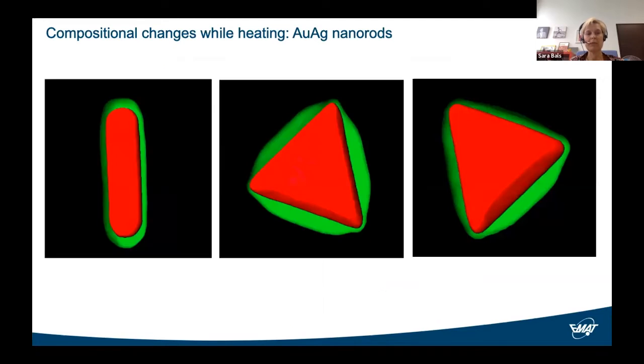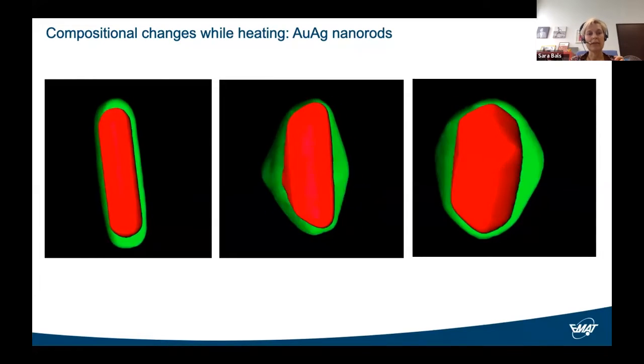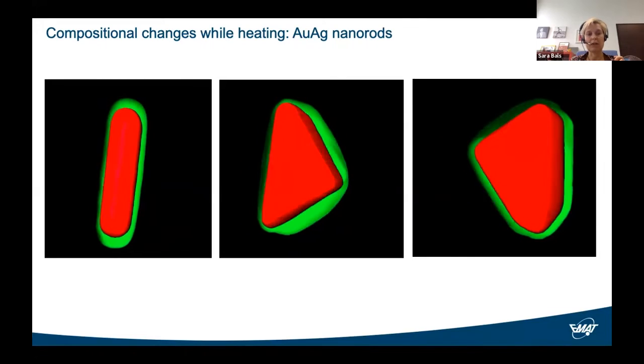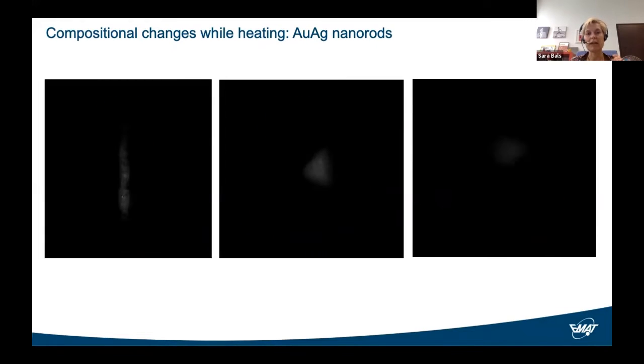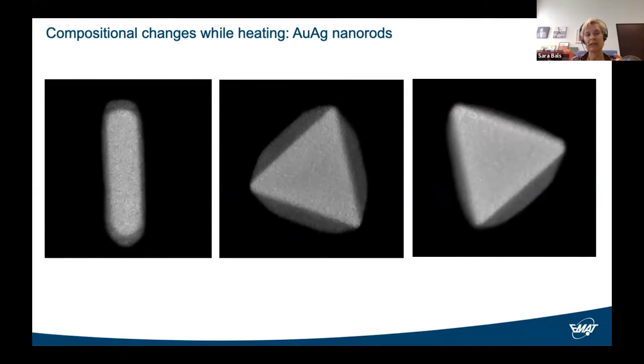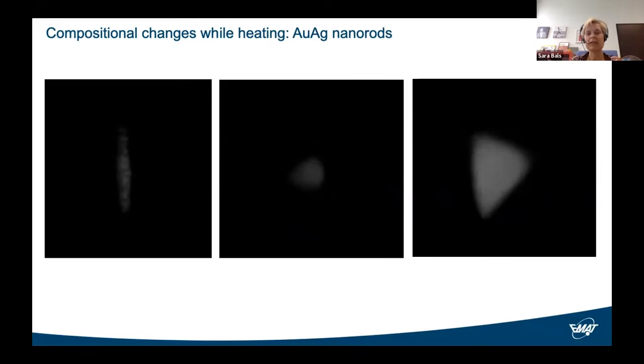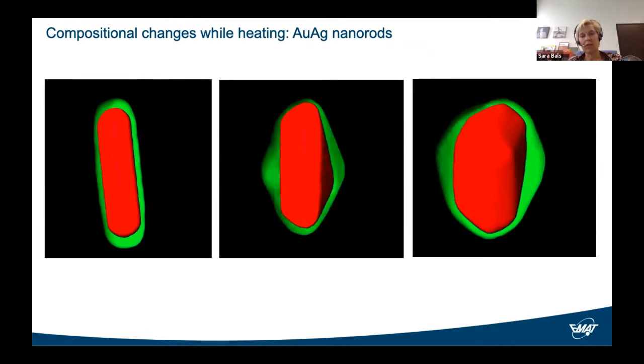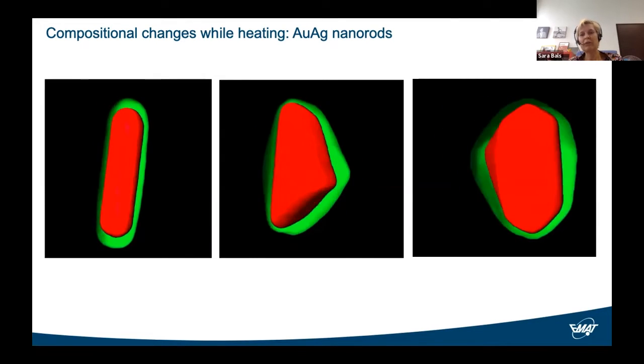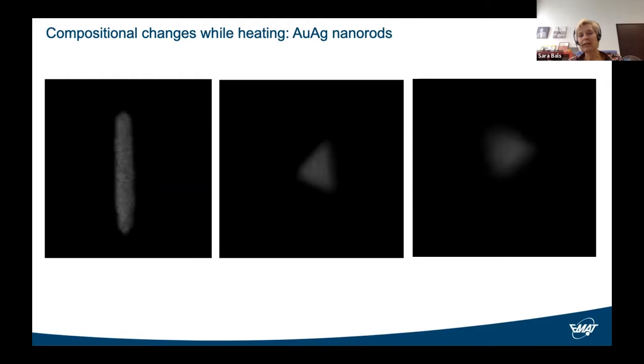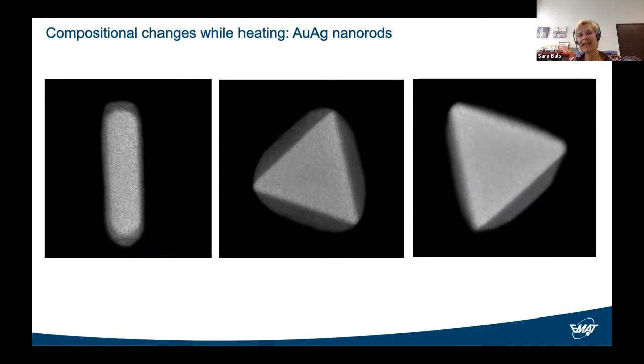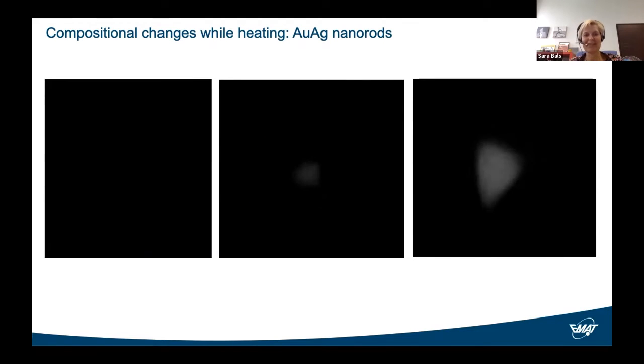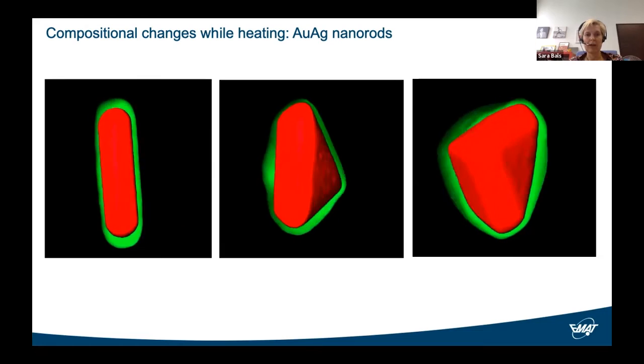So the experiment we will be performing will be done for these three systems. We have one core shell nanorod, two core shell nanotriangles, and the core shell nanorod and the nanotriangle in the middle have a composition of 60% gold, 40% silver. The nanotriangle on the right has 70% gold. And as you can see from these orthoslices, it's a tiny bit more asymmetric than the middle nanotriangle.